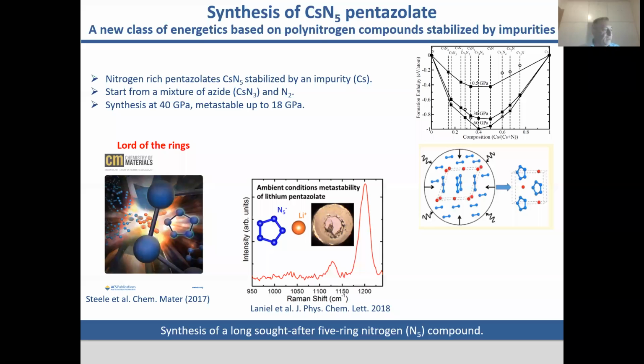And I think it is not surprising that other groups jumped on it. This is a paper published one year after from France, from Dominique. They used lithium, which has the problem with X-rays, but looks like it's better for quenching the material. And they managed to synthesize more or less the same compound with lithium that turned out to be stable at ambient conditions. So now you have a pressure that is almost accessible by large volume presses, and also it's quenchable at ambient conditions. Of course, more studies are needed, but I think this was a major breakthrough towards making things more applicable for practical applications.